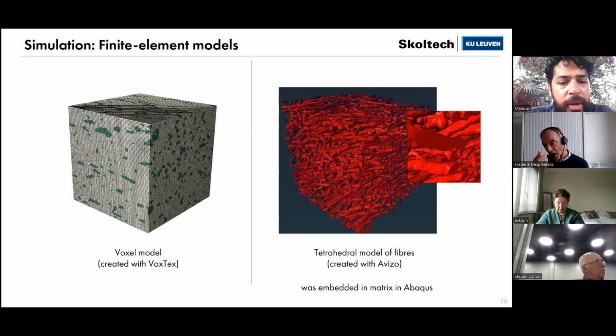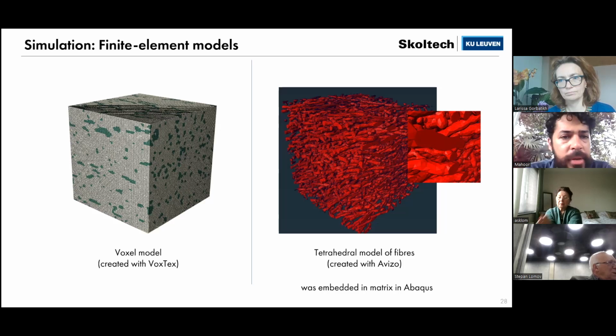Yes. And did you make any evaluation of whether the parameter set that you chose is actually a suitable set of parameters? Did you evaluate this, or did you just trust the results? Yes, it's a good question. I did it in my master thesis, but only for fiber orientation. So for fiber orientation, I have some relations for what size the voxel should be. But for models, I only considered 2 to 3 times smaller than the size of our descriptor. In our case, it's fiber. So basically only one case was considered. Yeah, but it's good to have an analysis of window sizes.